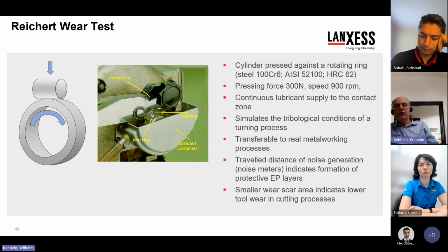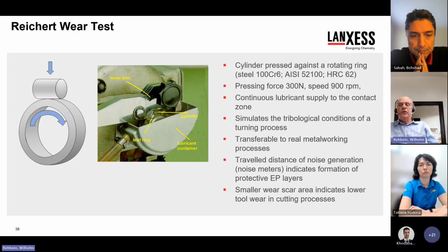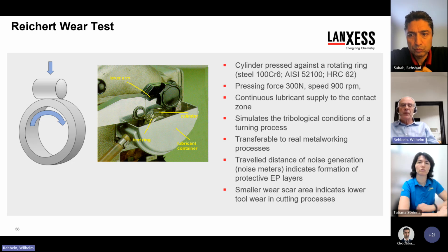Evaluation parameters are the travel distance of the noise generation. You can hear the noise very strong at the beginning of the test, and then after some time or some distance, the noise becomes much lower. And this point indicates the formation of a protective EP film on the metal surface. So a shorter noise meter is the better value. And also the size of the wear scar area on the cylinder after the tests is used for the evaluation of the different additives. And again, of course, a smaller wear scar area is the better result.